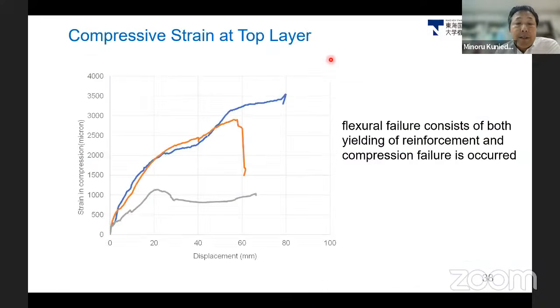So this is just information on the compressive strain at the top layer. As you can see, we have over 2,500 microstrain or more in the final stage, sometimes not reaching 3,000, maybe because we have delamination of the interlayer at the top layer.